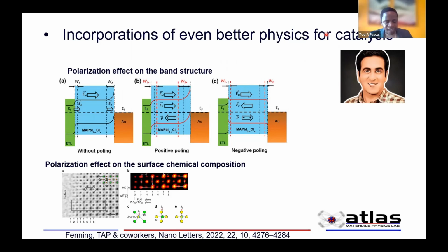If we know for a specific surface that we can target the rate limiting step and switch the surface such that the binding energy at the rate limiting step is reduced significantly, that means that we can accelerate the reaction resonantly, right?